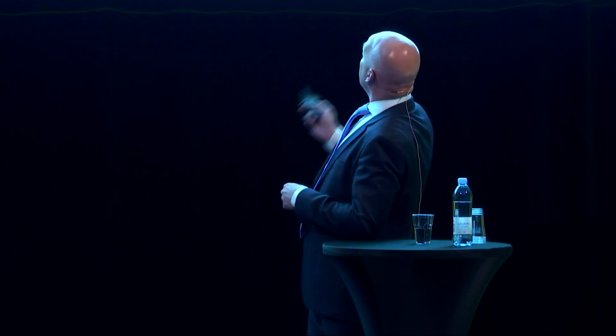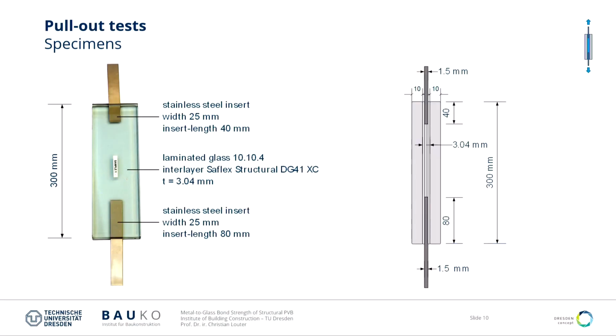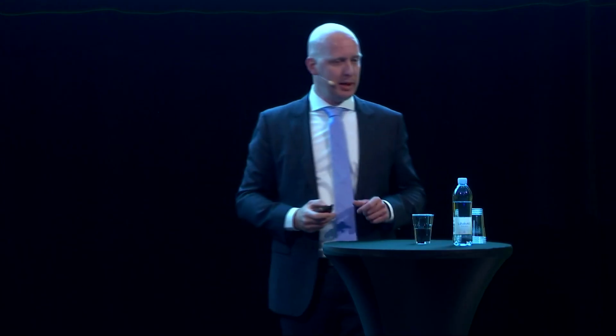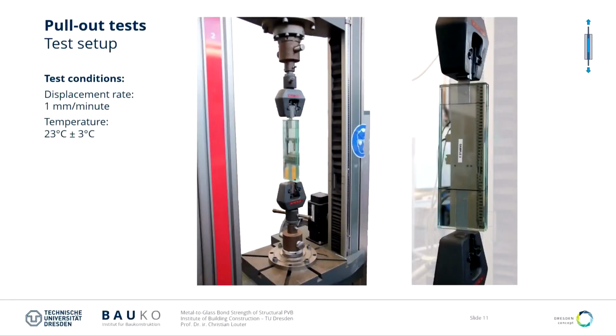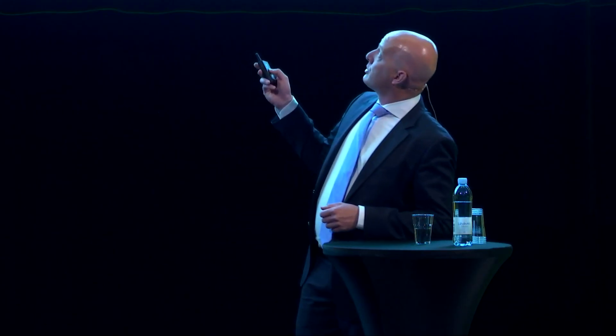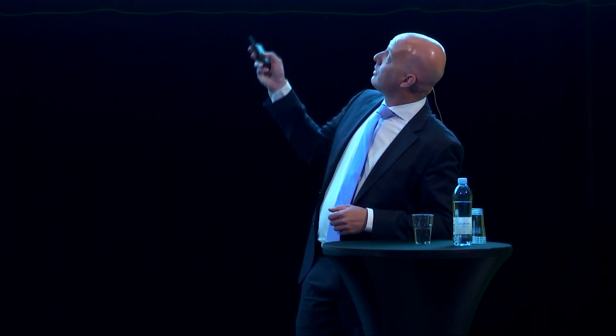And here you can see the cross section. You can see that we used 4 layers of structural PVB to reach about 3 millimeter thickness of the whole laminate. This is a test setup. We are then pulling the steel out of the specimen. So this is the glass. There we clamp the steel in this clamps, and then this one is moving up at a specific rate of 1 millimeter per minute. And we have performed these tests at 23 degrees without any temperature conditioning. So the fluctuation could be quite large, actually. So that's why there's, let's say, a margin of about 3 degrees on this testing temperature.